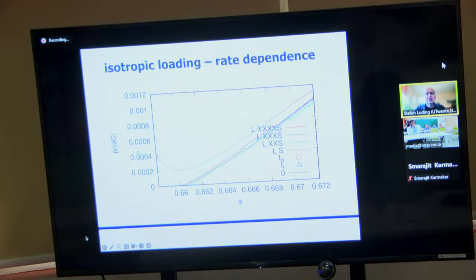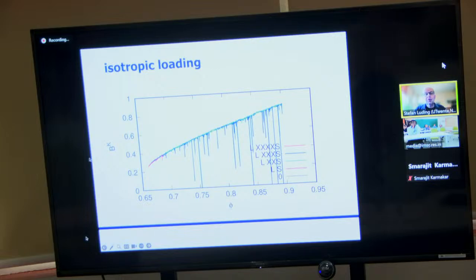Scaling it gives us pressure which is almost linear as a function of density or as a function of strain. I don't show the strain here. Okay, but there are these wiggles, these hiccups, these plastic events. A straight line would correspond to elastic, but everything which is not on a straight line is plastic. And this is the bulk modulus which we deduce, and the negative drops are the plastic events.